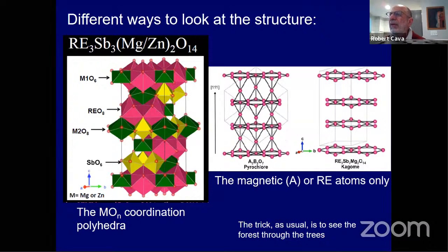Okay. So the whole trick, as usual, is to see the forest through the trees. The normal way of looking at solid-state chemistry is to draw the coordination polyhedra. That's shown on the left side here. And if you extract the magnetic part of this lattice, you put rare earths on these sites that have the cubes. If you put a rare earth inside every cube, which is where they sit, then you get this thing, which is a Kagome lattice here. And the relation between Kagome and pyrochlore is easily seen in this depiction of the crystal structure right here.